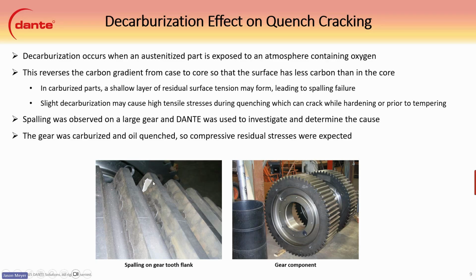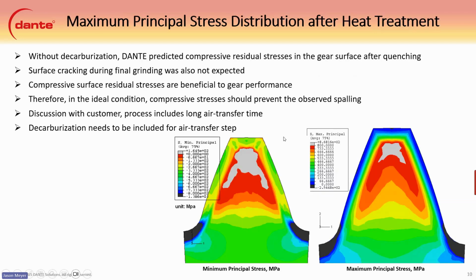In this example, the spalling was occurring in a large gear, and DANTE was used to investigate and determine the cause. This gear was carburized and oil quenched, and so compressive residual stresses were expected from the carbon case here. Without decarburization, DANTE can predict the compressive residual stresses in the gear surface after quenching. So you can see with the minimum and maximum principal stress here, the compression along the tooth surface. And that's because the